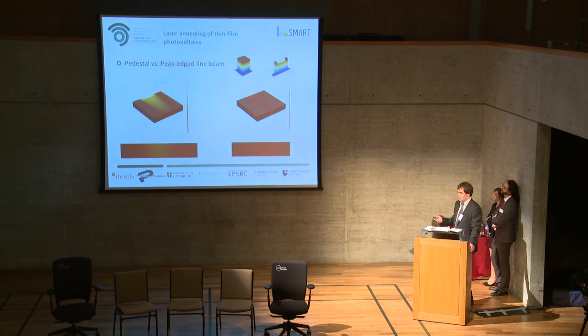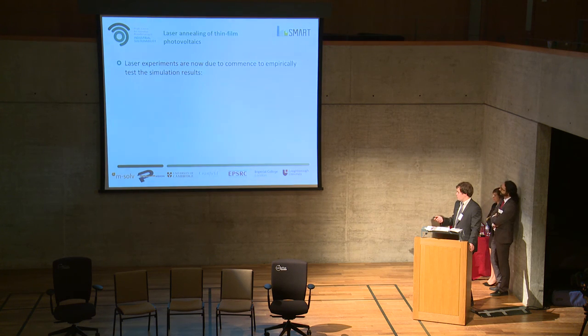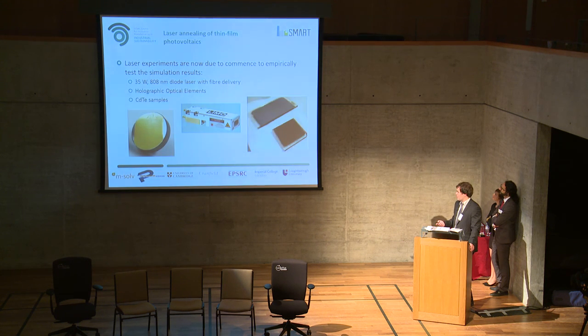So instead of using current processes, using an oven, for example, where you heat the entire panel up, all we're doing is heating the top few hundred microns. So three quarters of the glass is no longer heated, which reduces the energy use. So what we're due to do now is start actually testing these in experiments. We have a laser on its way, which is 35 watts at 808 nanometers. We have holographic optical elements in production, and we have cadmium telluride samples in production.